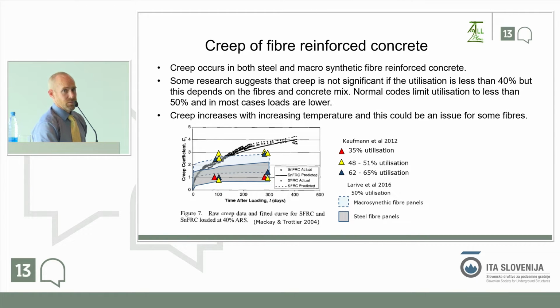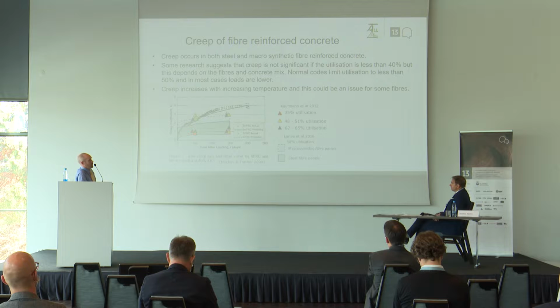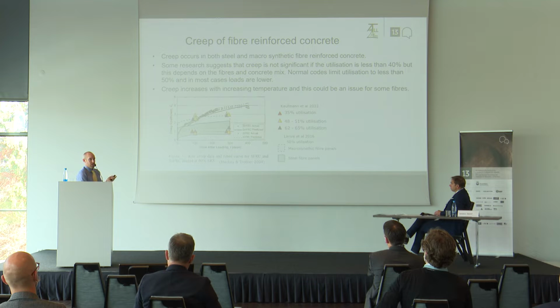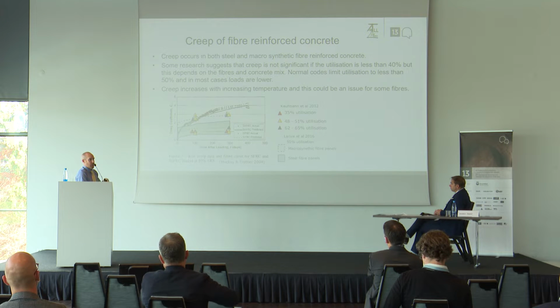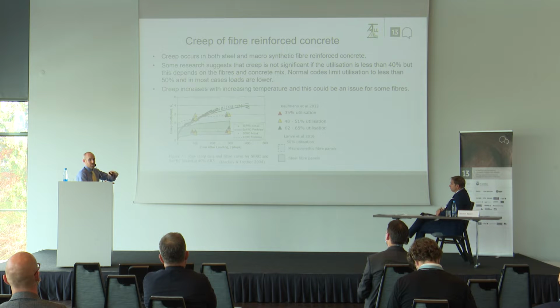So all concrete creeps. Now this is tensile creep. So bar reinforced concrete creeps in tension. And that's why we have coefficients in Eurocode, for example. Steel fibre reinforced concrete, that's that grey box, also creeps. And it's a similar, there was one sample with bars, which is a similar sort of area. So that creeps. Macrosynthetic fibres at low levels of utilization, so that I mean relative to the ultimate strength of your beam, if you're at a low level, let's say below 40%, which is basically where we'll always be because of the factors of safety that we have in our standard codes.